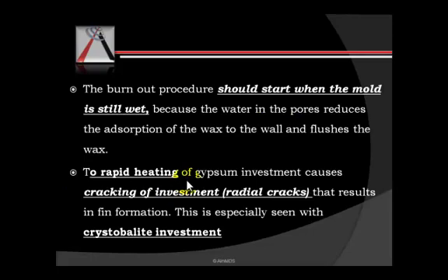Now the burnout process for the wax elimination should actually start when the mold is still wet. So we had our wax pattern, and our wax pattern was invested in the investment. This investment sets. Before it sets completely, the heating process to eliminate the wax should be started, because the water which is present in the pores reduces the sticking of the wax to the wall, and it helps to eliminate the wax more thoroughly. The water in the pores reduces the absorption of the wax into the walls, and it flushes the wax out of the mold cavity.